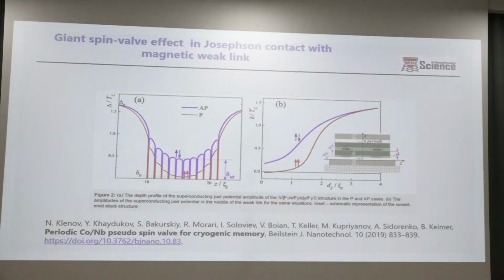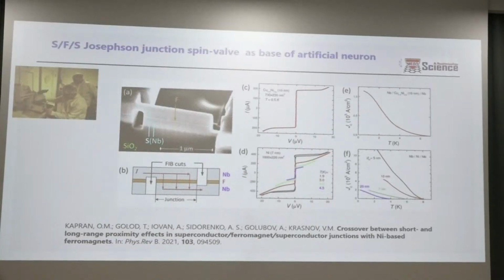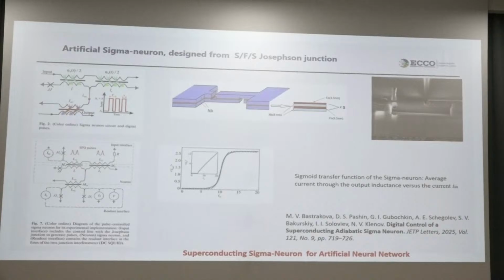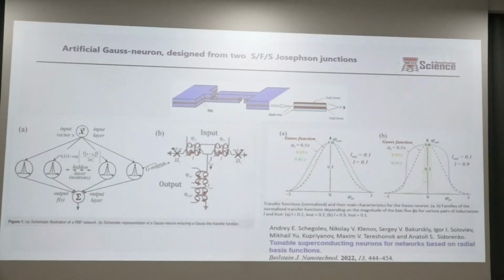And the base element which was prepared using such materials is the Josephson junction with a weak link between two superconducting layers, constructed from an artificial magnet. You can see that the blue and red curves demonstrate the critical temperature of this element depending on the mutual magnetization. On the TEM picture, you can see how this small Josephson junction looks, which can serve as a base of a neuron. Here a sigma neuron is constructed. This is a sigma-like characteristic, or a spike neuron or Gauss neuron with two such junctions. The spike neuron is an absolute analog of our neuron. In our brain, we have spike neurons. The excitation of a neuron with pulses goes from one neuron to another.